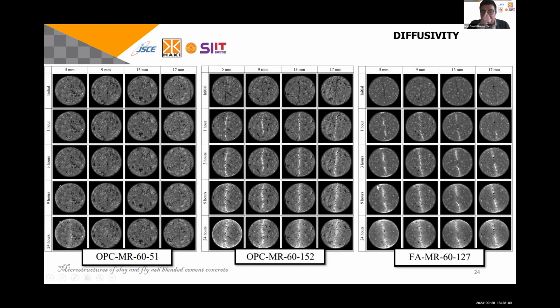And for the diffusivity test, as I said before, before we conducted the diffusivity test, all the specimens were immersed in the water for at least 24 hours. And then we conducted the diffusivity test. As I should mention before further explanation, we use a tracer. The X-ray CT itself can be combined for the diffusivity test, for the mechanical property test, for everything. Here, we combine 3D imaging with the diffusivity test along with the time: initial, 1 hour, 3 hours, 9 hours, and 24 hours.